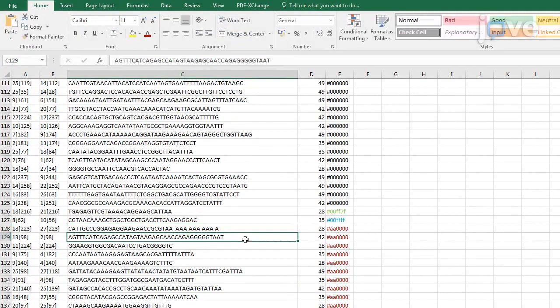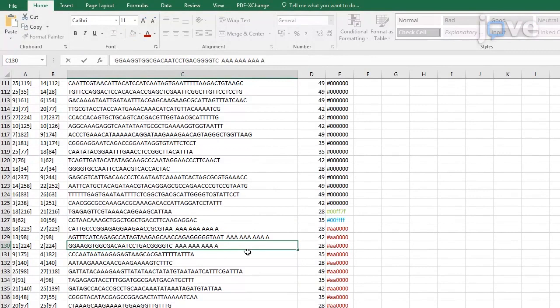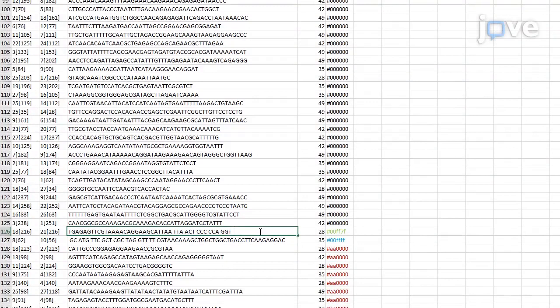Add a polyadenine sequence at the end of the staples to be used as handles for gold nanorod assembly. Modify the staple strands on the designed lock sites with lock sequences.